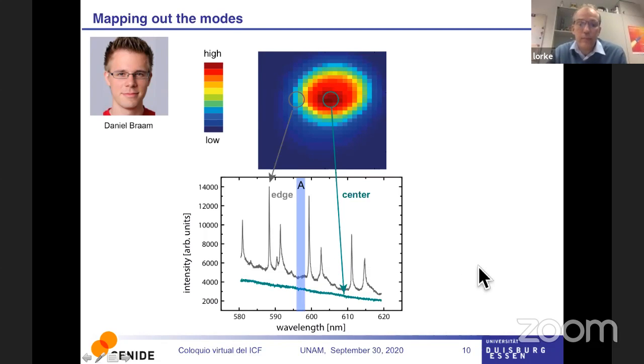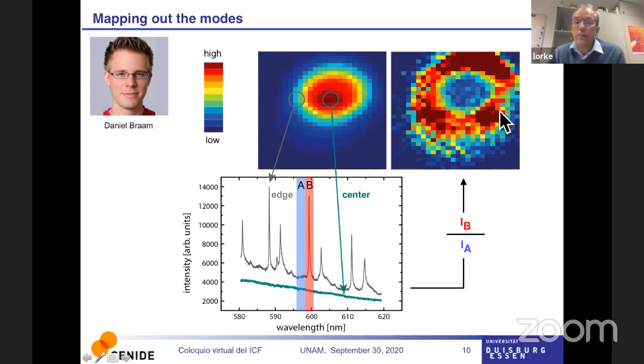So what he did was he took a certain range of wavelength depicted here, where in both of these you did not see a resonance, and another wavelength range where one had a very clear resonance and the other did not. And then he scanned the entire sphere and divided the integrated intensity in region A by the intensity in region B, or rather the other way around. And if you do that, you can very nicely map out where the resonance actually is active, and it's just as we expected. It's going around on the outside of the sphere. And if this doesn't really look like a sphere, that's not because it's not round, it's rather the uncertainty of the XY stage in the microscope.